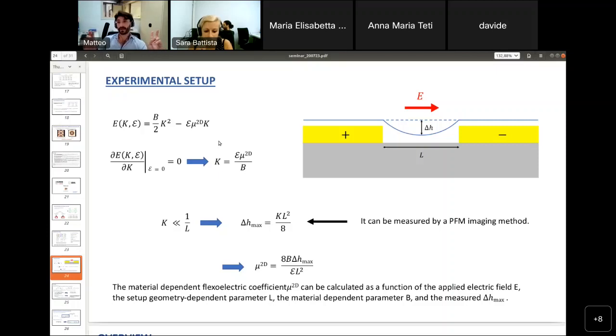Let me also specify that in this case we are assuming the deposited layer is non-interacting with the substrate. Actually, many times it does, because of van der Waals forces, but let me begin by considering it non-interacting. When we apply an electric field, for the effect that we mentioned, the layer is supposed to bend, and by a minimization of the energy functional, the curvature is given by the expression that we can see here, where k is equal to E mu over B.